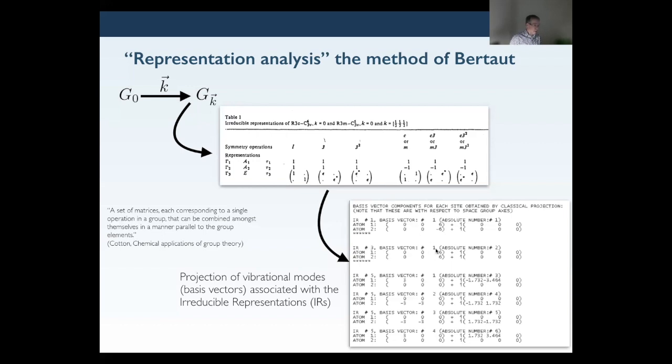If we look at the next irreducible representation, number 3, we again see only C components, now 6 and 6. So that will correspond to ferromagnetism, with both the components along the C direction being the same size. Irreducible representation 5 now involves 4 basis functions. Now this is starting to get a little bit more complicated to understand, because if you combine all of these basis functions, what's important is that it recreates all of the degrees of freedom of our system.